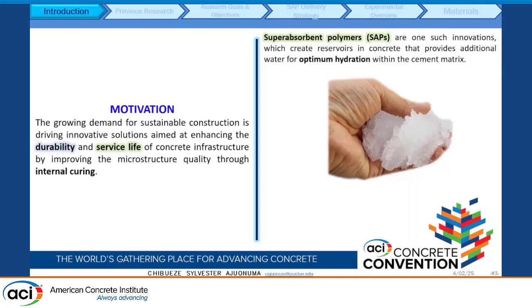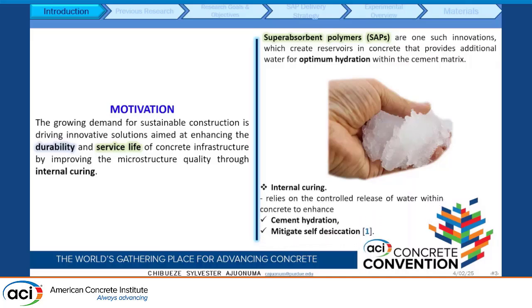We found out that internal curing and superabsorbent polymers, also known as SAP, are very key. They are one of these innovative solutions because they create reservoirs within the concrete, which provide additional water to aid hydration. Internal curing relies on gradual, controlled release of water within the cementitious matrix, which improves cement hydration and mitigates